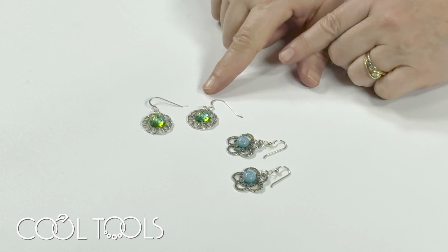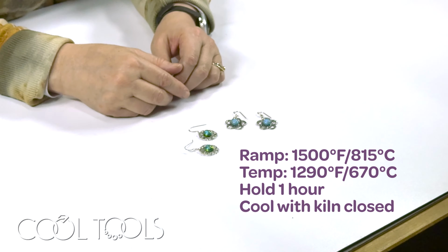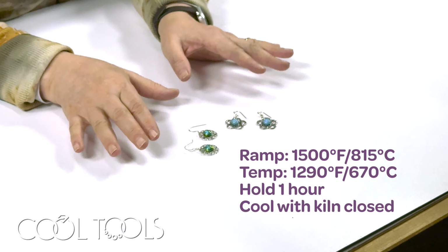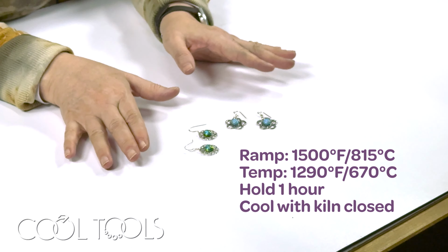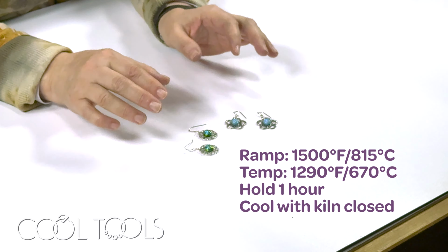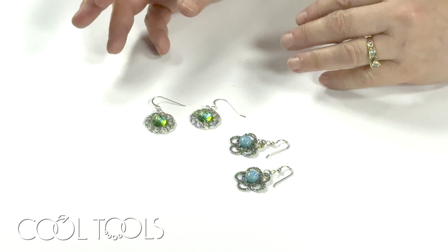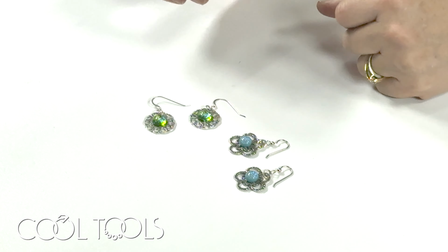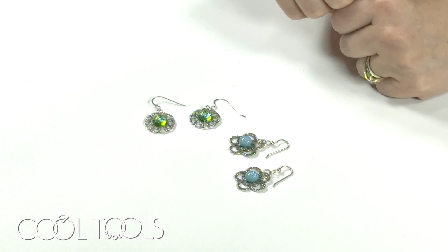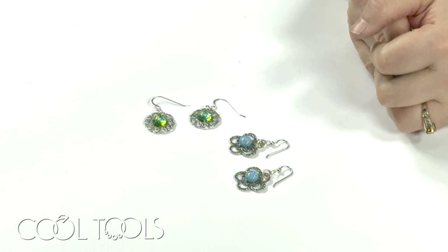When you're firing silver and glass together, remember that you need to slow down your kiln. I fired these for 1275 for an hour. You also need to leave the kiln closed while it's cooling down. Let the kiln get below 200 degrees before you open it. If you heat glass too quickly or cool it too quickly, you'll get what's called thermal shock, and either the glass will crack or it will pop off the silver. But as long as you use those slow ramp speeds up and the slow ramp down, you'll be just fine.